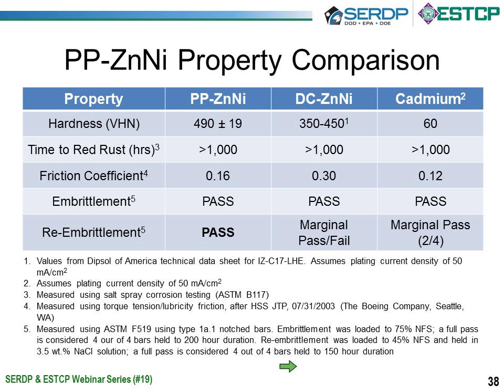So the last slide I have on this just gives an overview of the property comparison between the pulse-plated zinc nickel, the DC zinc nickel, and cadmium. You can see the pulse plating provides a higher strength over the DC. They all had great time to red rust and corrosion performance. The coefficient of friction of the nanomaterial was lower than that of the conventional DC zinc nickel material, and it was similar to that of cadmium.